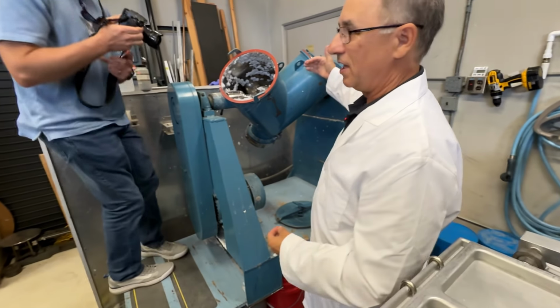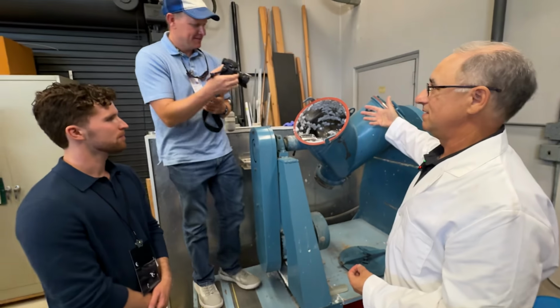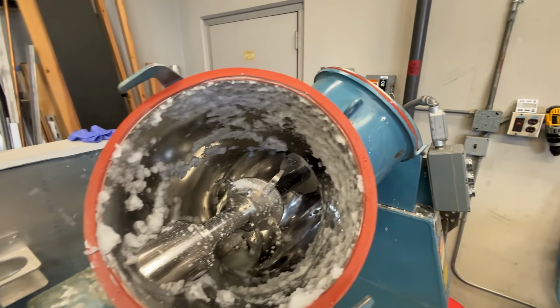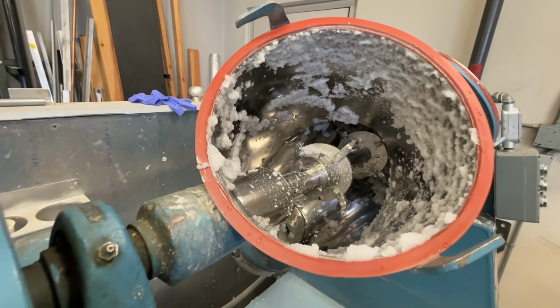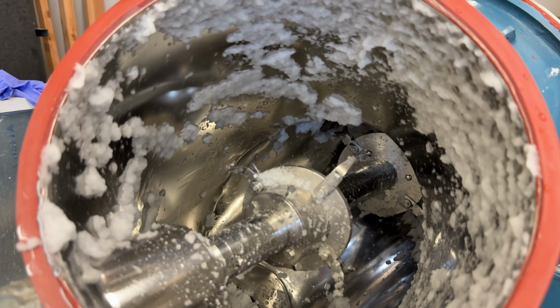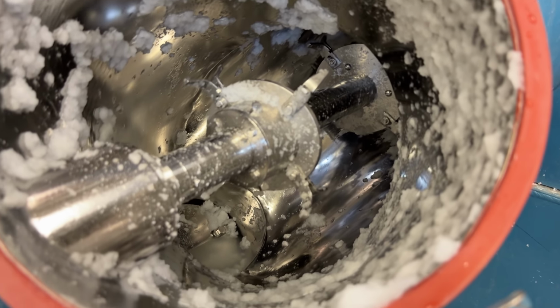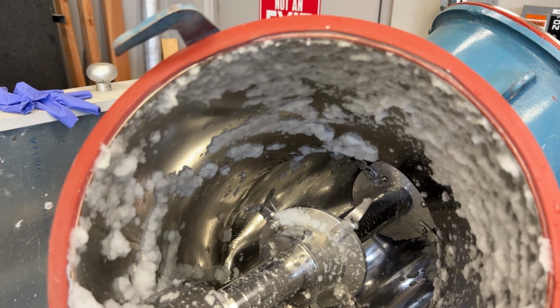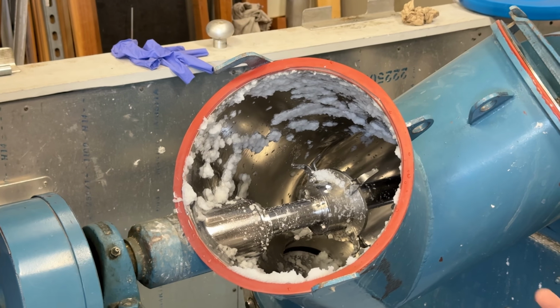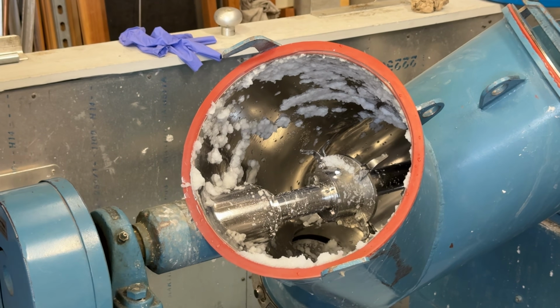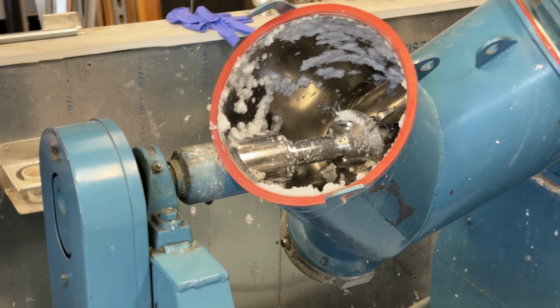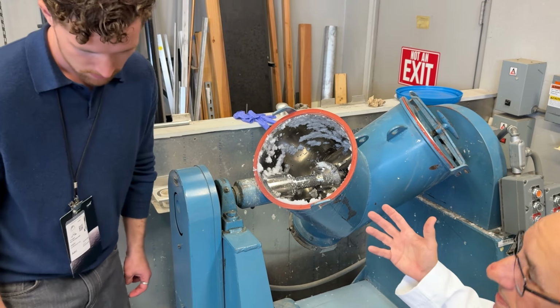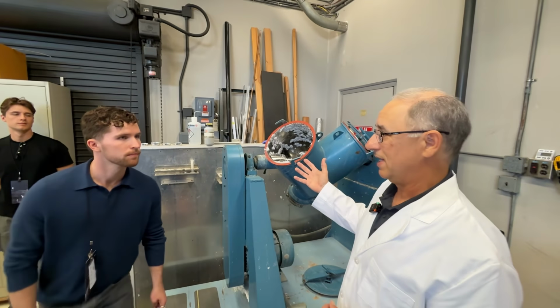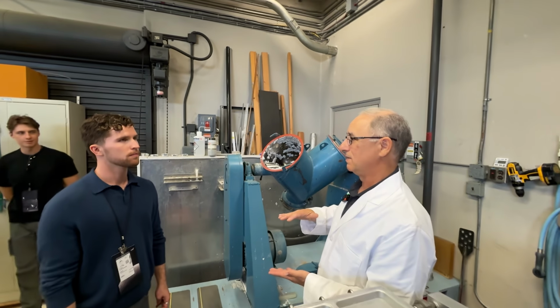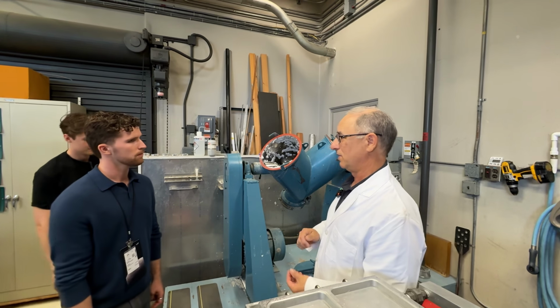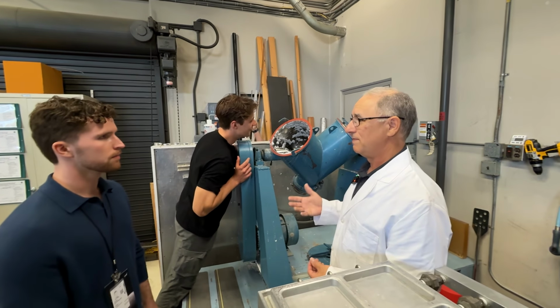So this shell rotates and hydraulically mixes the slurry, and as it goes back and forth in that hydraulic mixing, it passes by that intensifier bar that's rotating at about 4,000 RPM, and that chops the fiber. The amount of chop that you apply to the fibers determines the fiber length, and there's a really narrow window where you can achieve something as low as an 8-pound density tile or scrap. When you go for 17 to 20 pound per cubic foot densities, it's much easier to get because you're pressing them to a higher pressing depth.